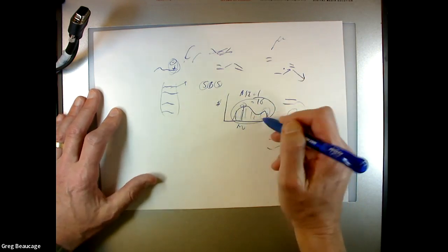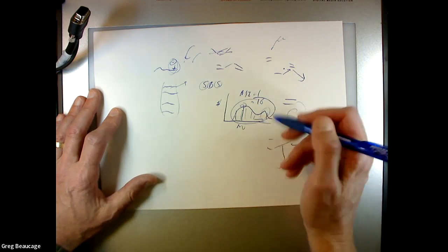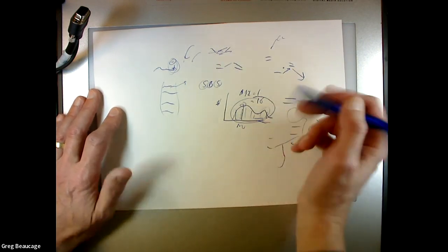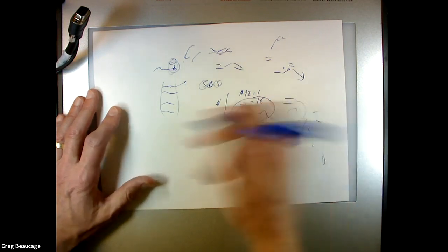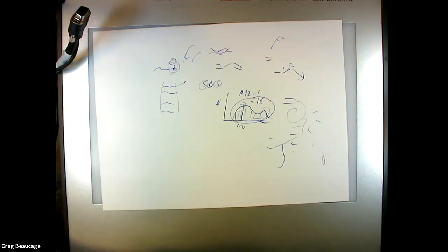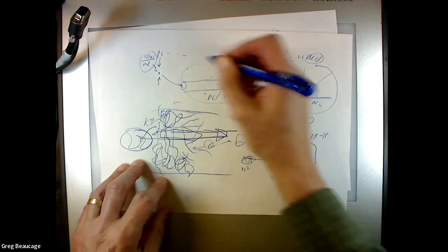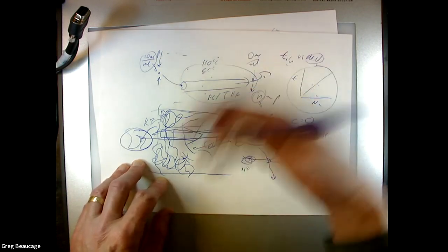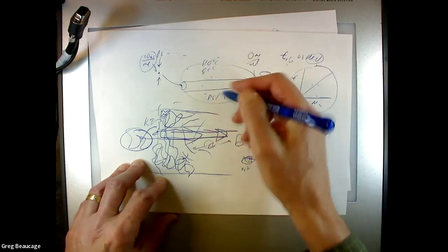But for this commercial sample of polyethylene, which is the most popular polymer, almost tied with polypropylene, I think. And polypropylene is going to be polydispersed like that too. So basically, you want to get that plot and put it in the GPC. The problem is for polyethylene, you have to run it at high temperatures. You have to have this whole thing heated to like 110 or 80 degrees C to dissolve it. That leads to problems and can precipitate out the polymer. So you need a special GPC for that.